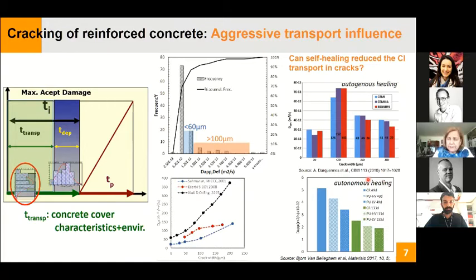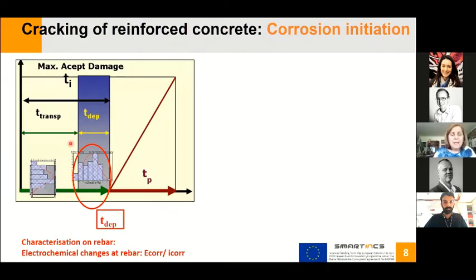Also, this effect has been observed with autonomous healing that depends on the type of self-healing agent. In this case, it was polyurethane. This was also addressed by Nele De Belie in his talk, and they also observed a decrease in the chloride transport. So there are preliminary results that indicate that self-healing can contribute to and enhance the durability of cracked structures.